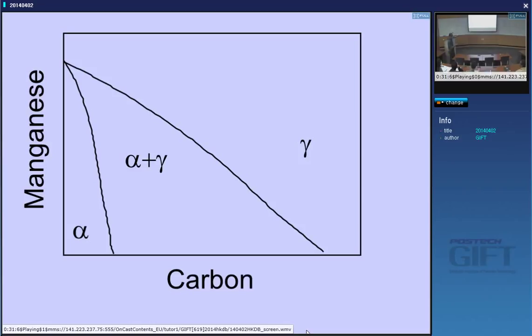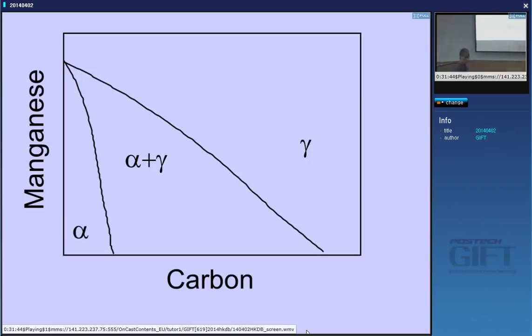Why almost identical? Because in this case there is no diffusion of manganese since the spike has become physically meaningless. But if the carbon is different in the austenite, then even though there is no manganese diffusion, you will have a slightly different manganese concentration. Strictly speaking, paraequilibrium means that the ratio of manganese to iron atoms remains constant, not the absolute concentration. So there will be a slight gradient, but it's so small that we can say the tie lines are horizontal.